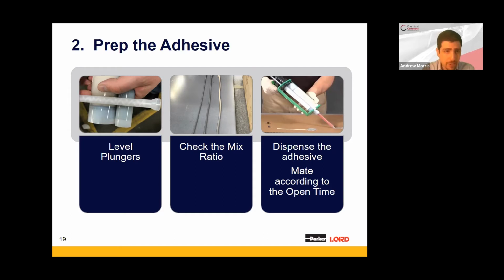So if you see the picture on the left, the reason we do that is you can see out of the factory, they fill up the one side of the cartridge, it's moved to somewhere else, another operation, and then the other side of the cartridge is filled. So there's often a slight discrepancy of one side or the other will have an additional adhesive. By doing that check to make sure that you're having both components coming out of the adhesive at the same time, you're ensuring that you're getting the proper mix.